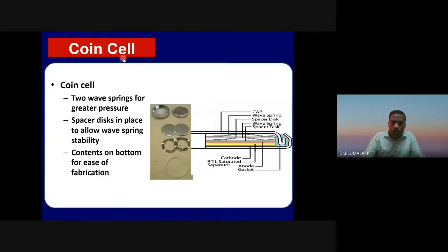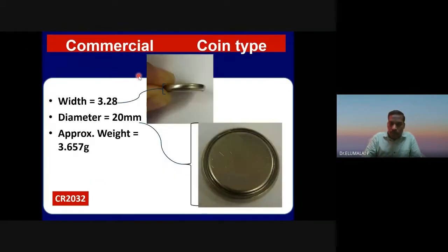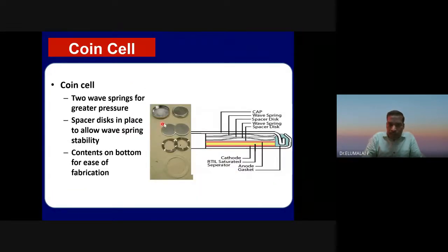How it is done? This is how it is done. Take the electrode material, make it as a paste, apply it on a current collector, a conductor, maybe carbon cloth or nickel foil, aluminum foil, gauze, etc. To make a coin cell, you crimp some portion so that it will go inside exactly. It should go inside this. Typically the size of this electrode will be about this much.